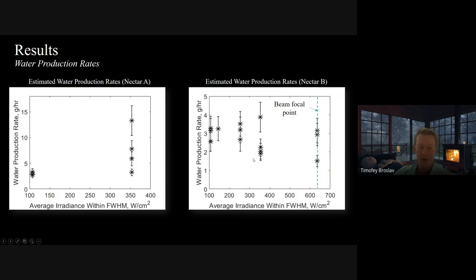Now, for water production rates, these were estimated using the residual gas analyzer. Nectar A on the left has a positive correlation against the average irradiance of the beam. Nectar B does not. It seems stagnant compared to the actual irradiance of the beam. It also has a much lower water production rate than Nectar A.